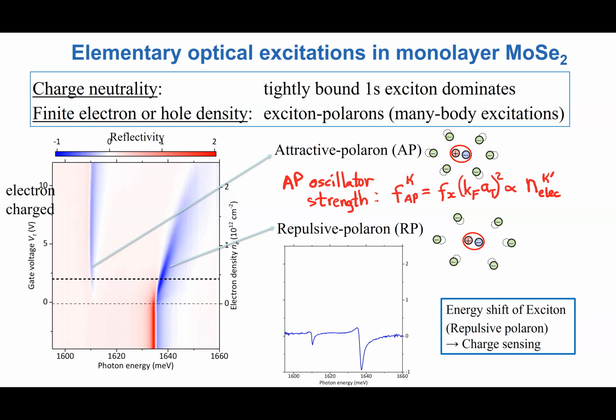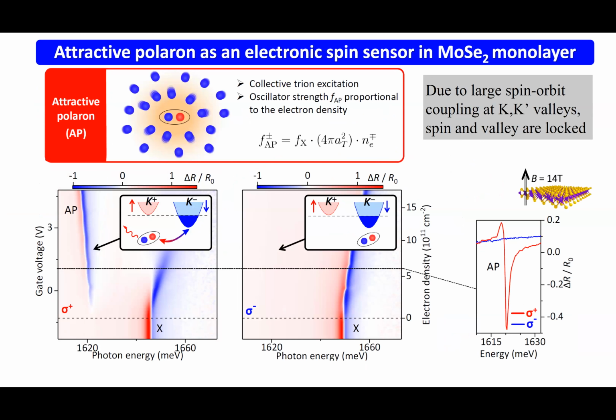And I will try to show you with these experiments that they're taking at 14 or 16 Tesla. So basically, as you go to 14 Tesla, what happens is that the valley Zeeman effect is large enough that you have a finite electron density. All the electrons occupy one valley, right, because it's energetically not favorable to occupy states of the opposite valley. Of course, this is a misleading picture, so we no longer have parabolic bands. We have multiple Landau levels that we are occupying, but it's two signatures you see here, but I won't go into that. So basically, we go to a scenario where electrons are all in, say, minus K valley.